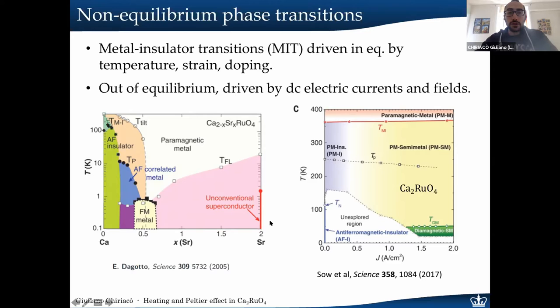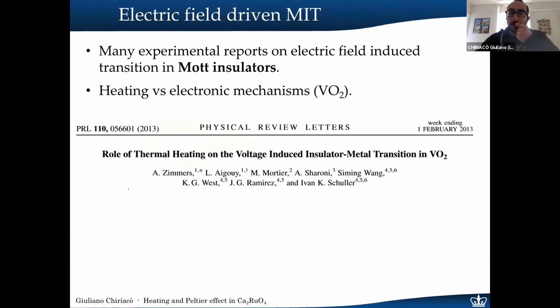Recently there have been many experiments performed out of equilibrium, in which the transition in a certain material is driven through electric currents or electric fields. You can see this in the phase diagram, again for calcium ruthenate, in which you have as tuning parameters the temperature and the applied current, and you can drive many non-equilibrium phases through the application of this current. Now these experiments have been focused mostly on inducing the metal-insulator transition in Mott insulators.